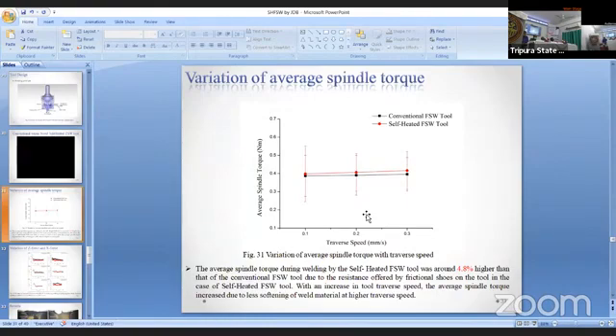So we can say that due to the resistance offered by the frictional shoe, the average spindle torque has increased. And it has been seen that as we go on increasing the traverse speed, the average spindle torque increases. The reason is the less softening of the weld material. If we increase the traverse speed, the heat input to the material will be less, and that's why less softening of the weld material will take place at higher traverse speed. That's why we can also say that the average spindle torque will increase.